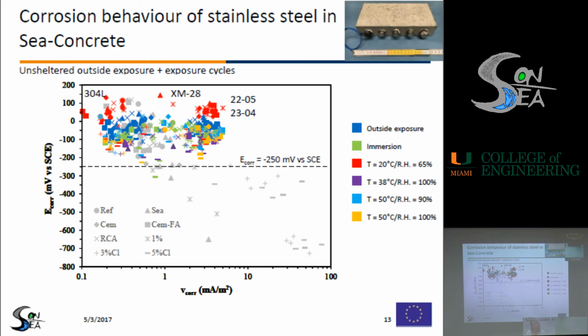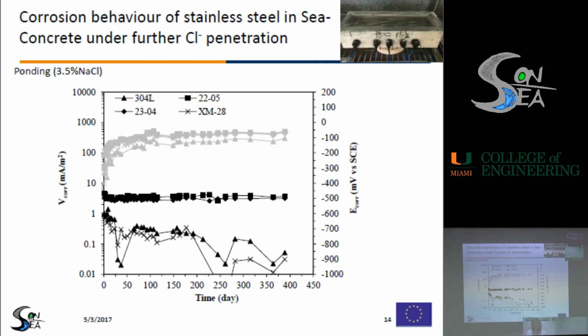In order to study their behavior when further chloride penetration is expected, the specimens were exposed to the ponding test. These are the results obtained during 1 year of exposure on the different types of stainless steel embedded in the sea concrete. So, besides the initial chloride content, we have to take into account the further penetration of chloride. We can observe that both corrosion potential, the gray symbol, and the corrosion rate, the black symbols, were stable during the exposure period, indicating that corrosion did not occur during this year of exposure.